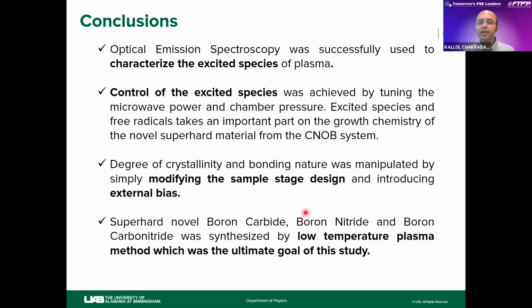Degree of crystallinity and the bonding nature was manipulated by simply modifying the sample stage design and introducing the external bias. Superhard novel boron nitride, boron carbide, and boron carbonitride was synthesized by the low temperature plasma method, which was the ultimate goal of this study.